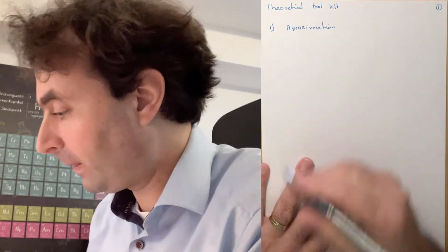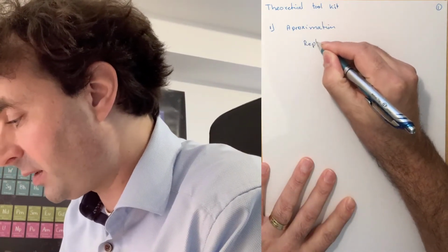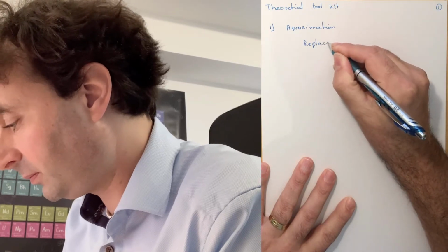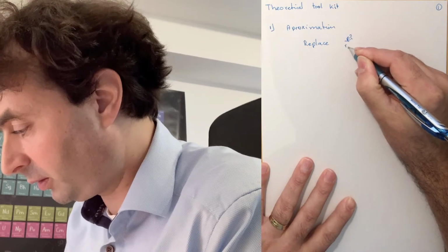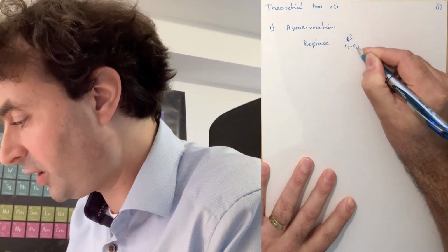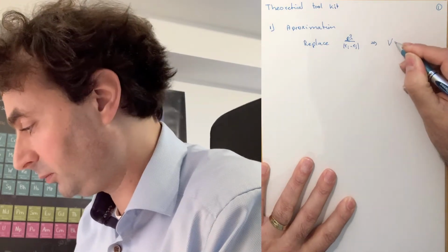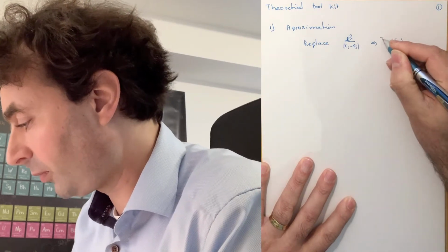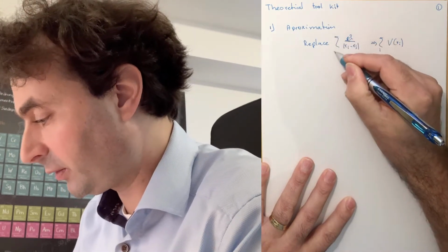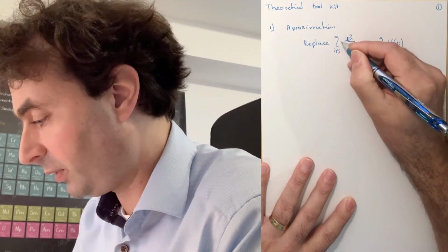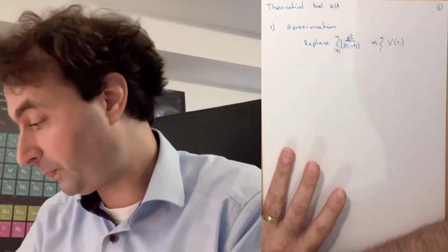results. And one approximation that has been very successful is to replace the Coulomb interaction, e squared over |r_i minus r_j|, by a potential. For a potential we only have to sum over the coordinates of one electron, and for the Coulomb interaction we have to sum over all pairs of electrons.